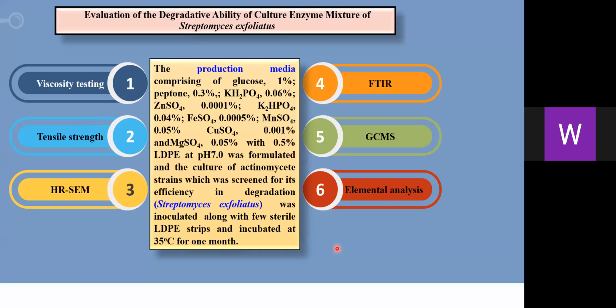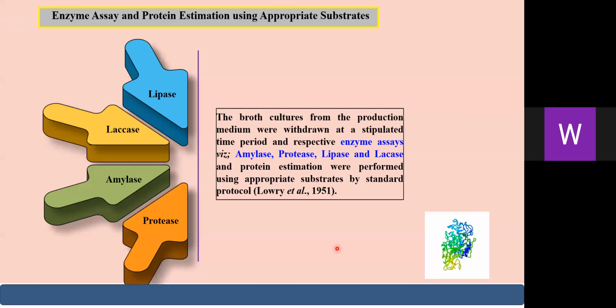Evaluation of degradative ability of the culture enzyme mixture of Streptomyces exfoliatus. Among the 5 strains, Streptomyces exfoliatus exhibited the maximum degradative ability. Henceforth, it was inoculated in the enzyme production medium along with the LDPE strips and incubated at 35 degrees centigrade for 1 month, and thereafter physical, mechanical and chemical analyses were performed: viscosity testing, tensile strength, HRSEM, FTIR, GCMS, and elemental analysis.